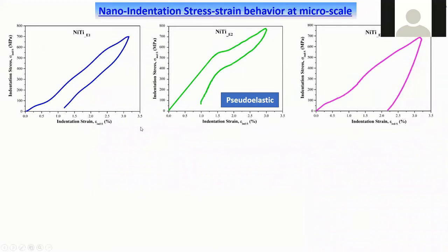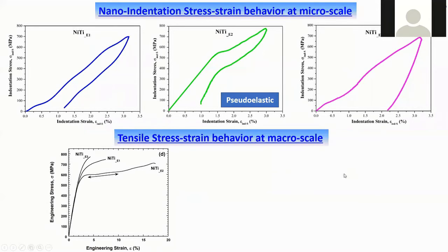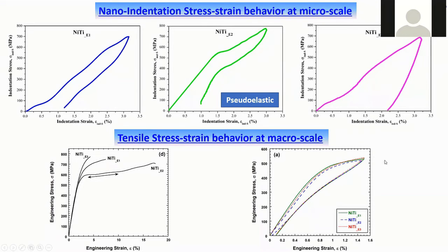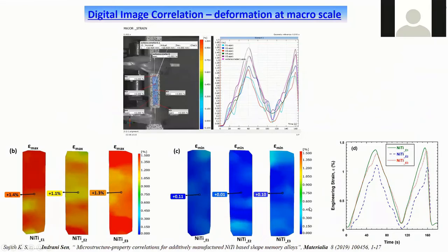When we found the stress strain curve from the indentation results, we again have seen that this alloy shows some pseudoelastic behavior, which is not apparent from the other alloys prepared with different laser energy densities. And when we looked at their behavior at the macro scale, we made real life tensile specimens and looked into the tensile properties. We have seen that the one of our concern is showing much higher pseudoelastic recoverable strain. We confirmed the recoverability of strain as well by loading and unloading.